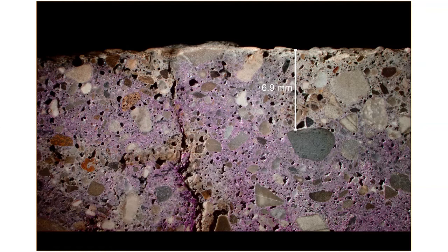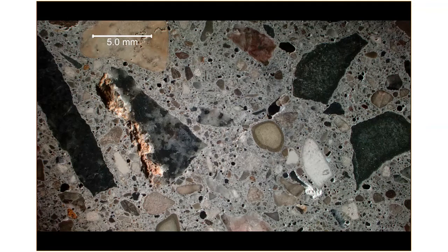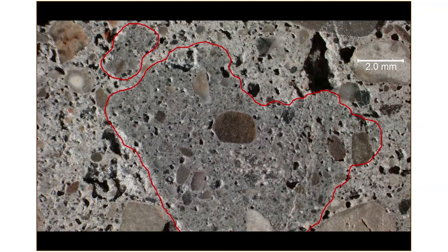Now we look at concrete a little farther down, and we see the aggregates used. Some crushed aggregates in here, some pea gravel. Here's some pea gravel. If you're seeing the cursor, we have some aggregates that were crushed. We don't know the significance of that, how much of that aggregate was crushed, how much of it was natural gravel. Some other interesting anomalies we see are these darker masses, and these were just poorly mixed areas in this concrete, in these two lifts of concrete.